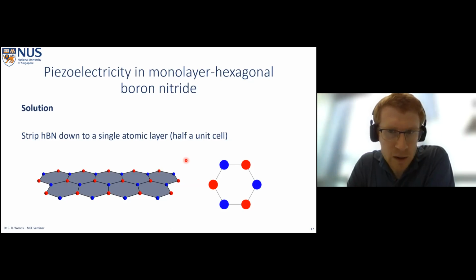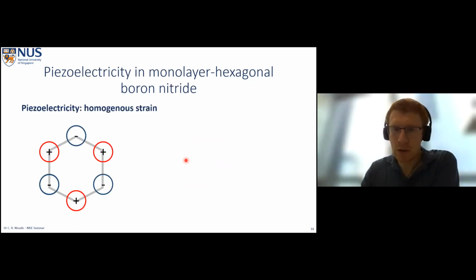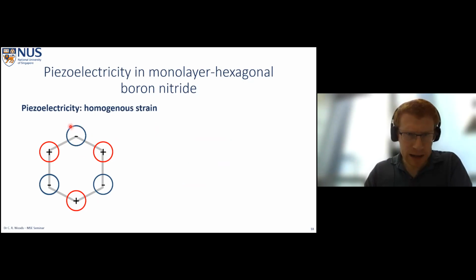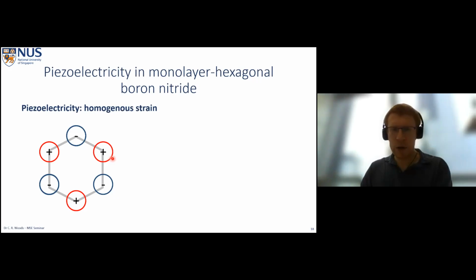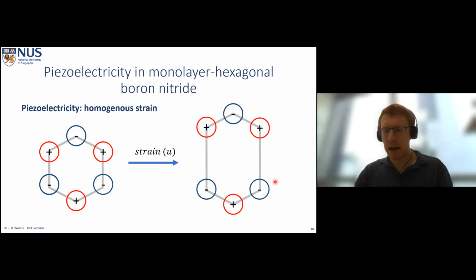In this case, we use half the unit cell, and we no longer have centrosymmetricity, and so we should see some piezoelectricity. So how does piezoelectricity work for hexagonal unit cells like this? Well, we need a polar bond, which we do. We have negative and positive atomic cores. Negative in our case would correspond to the nitrogen atoms, positive to the boron. And then we have to introduce some strain like this, and we'll get a polarization field associated with the fact that we've now split the charge